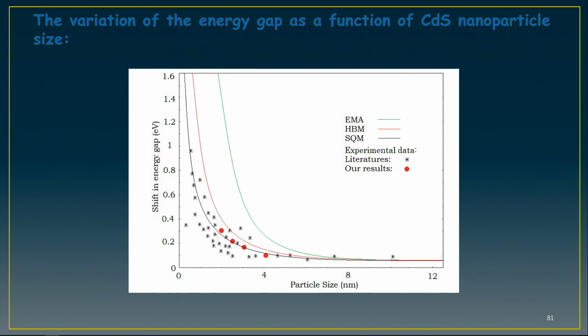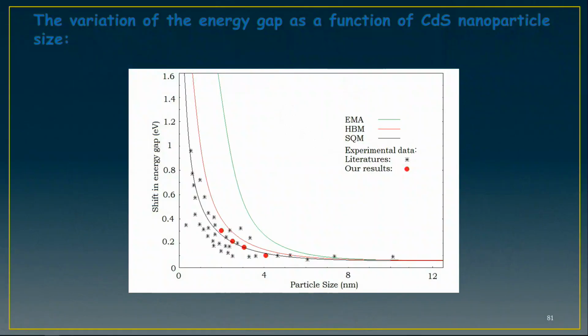The green is the effective mass approximation. It comes from the particle in a box, the general particle in a box in quantum mechanics. The hyperbolic band model is shown, and the experimental results. These four circles are our experimental results, which match with the hyperbolic band model. And also the stars are the experimental results which we obtained from the literature.